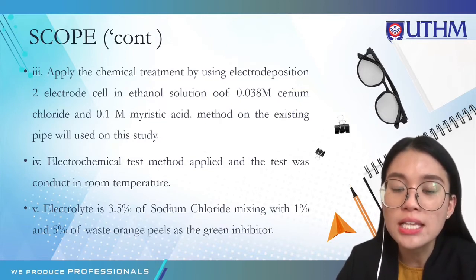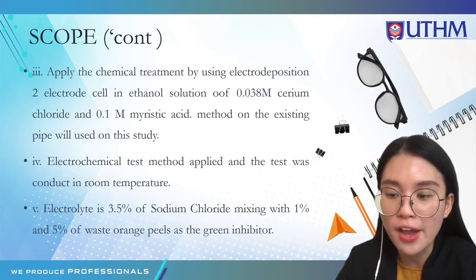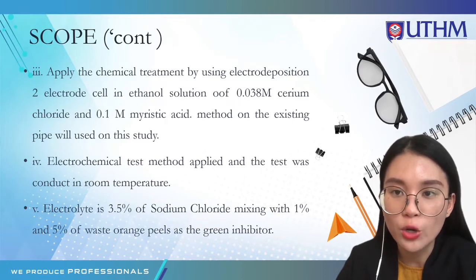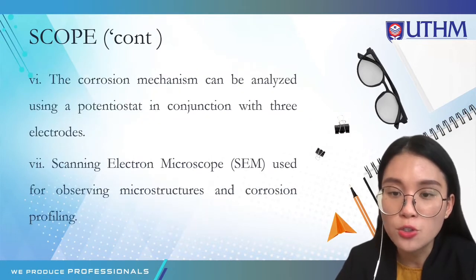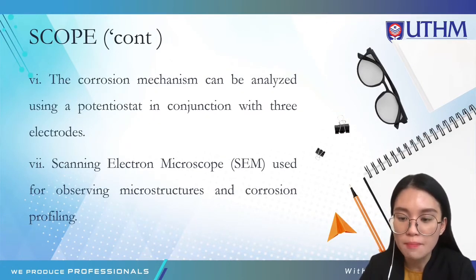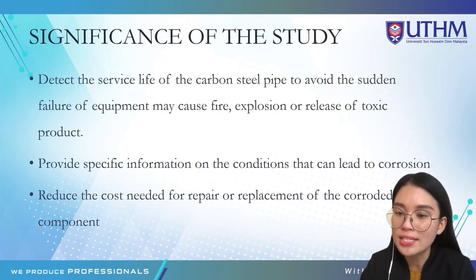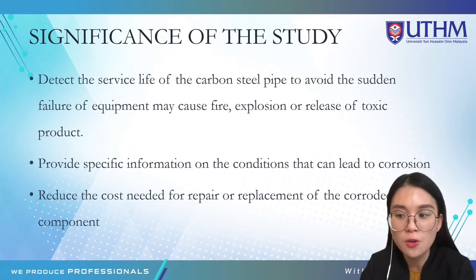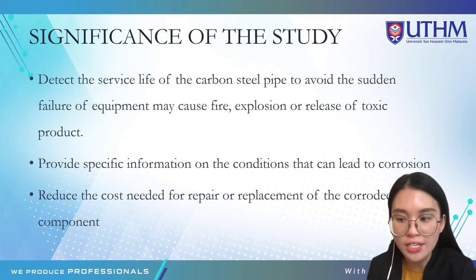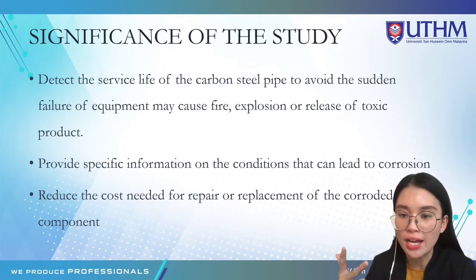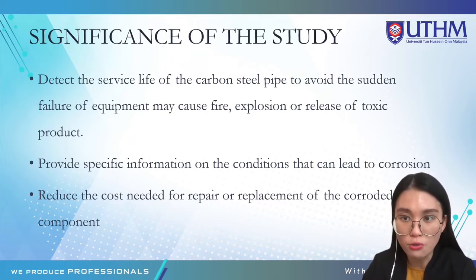The electrolyte used is 3.5% sodium chloride, mixed with 1% and 5% waste orange peel as a green inhibitor. I also use Scanning Electron Microscopy (SEM) for observing microstructure and corrosion profiling. The significance of this study is to detect the service life of the carbon steel pipe, to avoid sudden equipment failure that may cause fire, explosion, or release of toxic products, and to provide specific information on conditions that can lead to corrosion, thereby reducing repair and replacement costs.